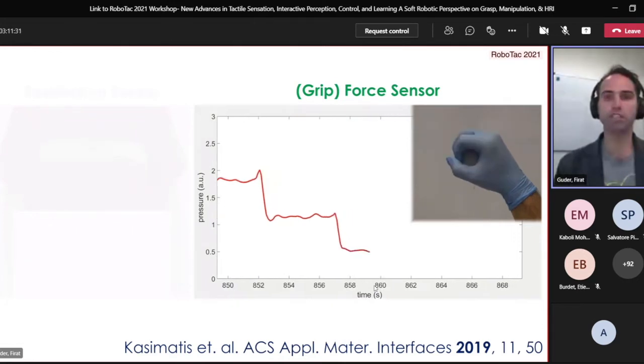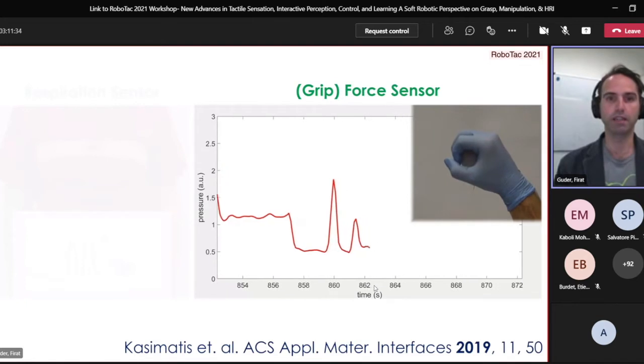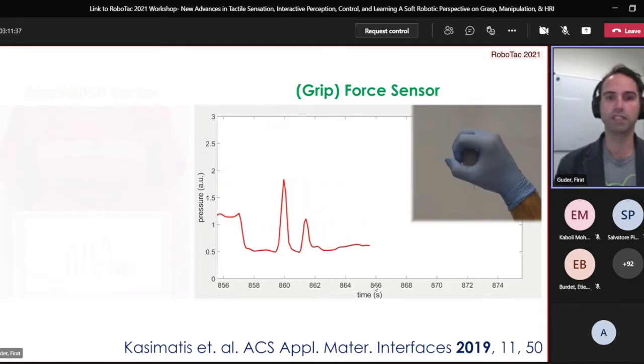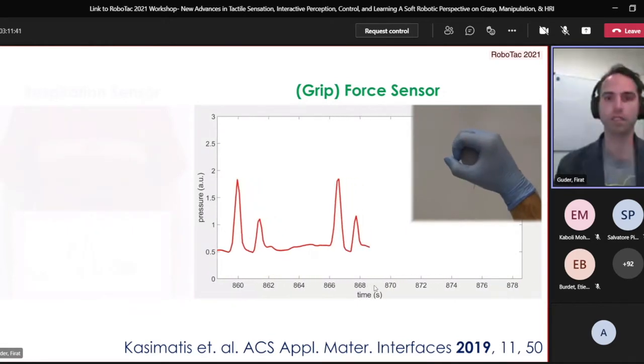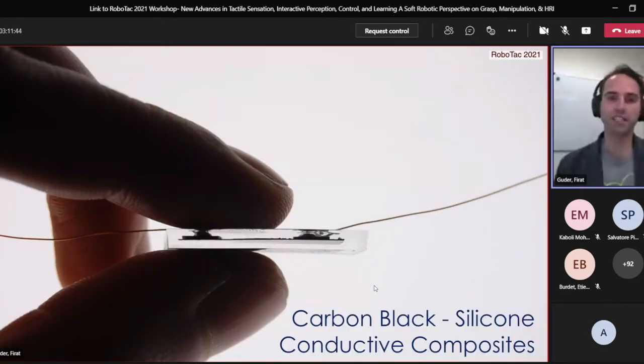But what you're seeing right now is that the user is squeezing a rubbery ball, which we can sense in real time, the gripping force. So the way we created these force-sensitive materials is by using a conductive stretchable polymer, which we have produced in the lab. And it's just a simple composite of carbon black, so conductive carbon particles, and silicone polymers, so silicone elastomers. And these materials are fairly well known in the materials community for sensing touch.